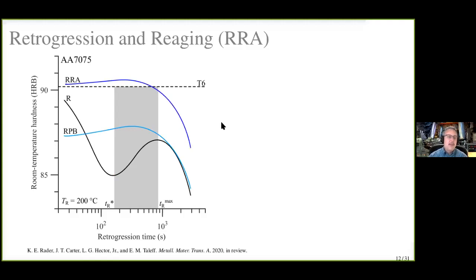Let's take a look at that. So here we have the retrogressed material, and then here we have the material after reaging. And what you will see is that this hardness after retrogression and reaging is higher than the T6 hardness was originally. So this is what the retrogression and reaging process buys you: T6 or higher hardness and strength with improved stress corrosion cracking resistance. Now, the reaging times here were about 24 hours at 120 Celsius. So that's a typical reaging heat treatment. It's also the same as the original aging heat treatment to get the T6 condition.